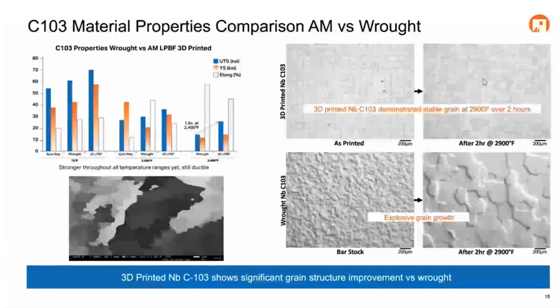So in the AM version, we can still see that retained weld macrostructure that we get from the process. And so this material is going to be very thermally stable and have better properties that don't degrade at higher temperatures through the service life of the component, versus the raw material.